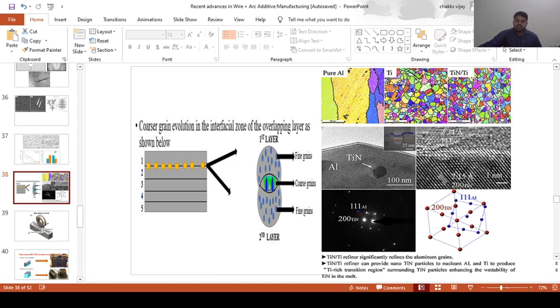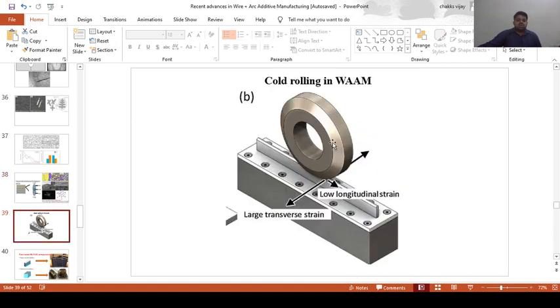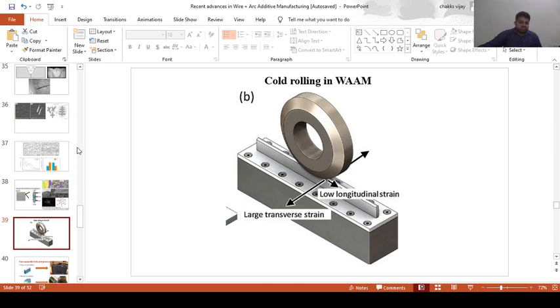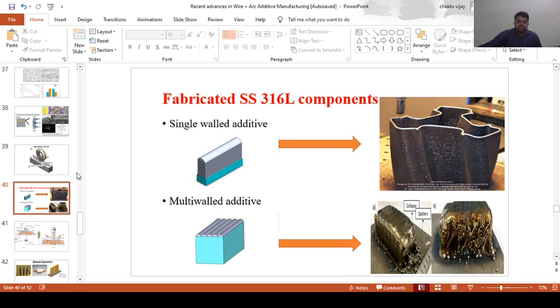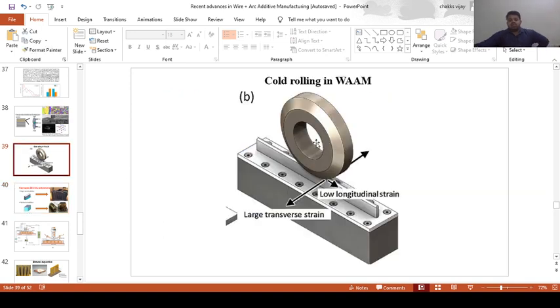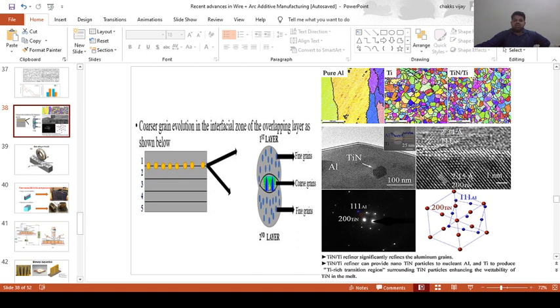If you use titanium nitride, which has very strong potential as a heterogeneous nucleant, it can refine to very fine grain. Either we can use this kind of grain refiner, or else we can go for a rolling operation, which I was supposed to discuss earlier, but this slide came a little late. After the end of each deposition, we perform rolling by applying a very high rolling pressure, like 80 kilonewton, 100 kilonewton, 200 kilonewton, so that grain refinement is possible without any grain refiners.